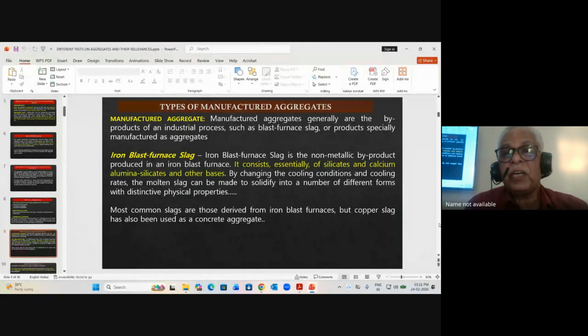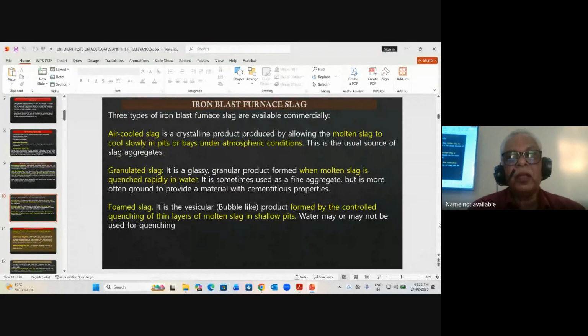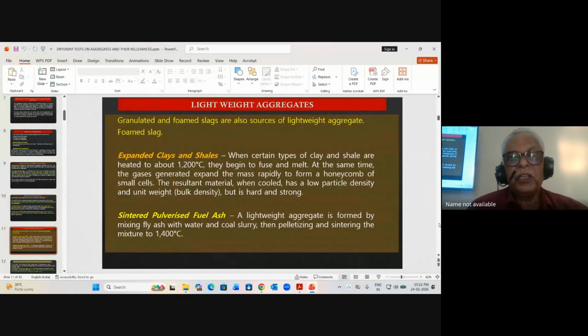By changing the cooling conditions and cooling rate, the molten slag can be solidified into a number of different forms. Most slags are derived from iron blast furnaces, but copper slag has also been used as a concrete aggregate. Air-cooled slag, granulated slag, and foam slag are typical examples of iron blast furnace slags. I will not go into much detail on it.